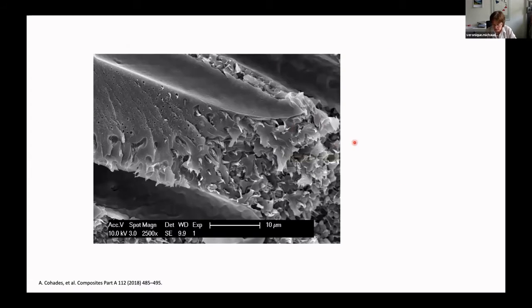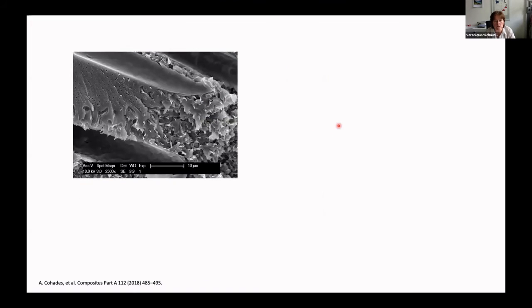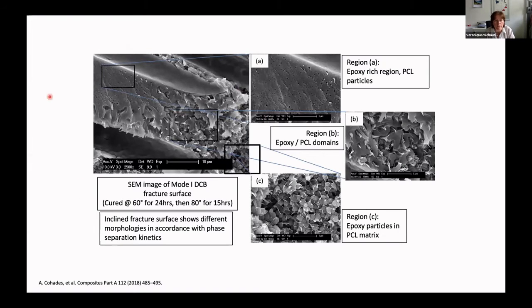It was a bit messy, but if you look in more detail, you see here that you have regions where you have an epoxy-rich region with some PCL particles that you can see here. Some regions had a mix of epoxy and PCL intertwined domains. And by the way, you can see the PCL on the fracture surface is quite elongated, so it does its job. And then some regions had the epoxy particles in a PCL matrix, which is the microstructure that we like.